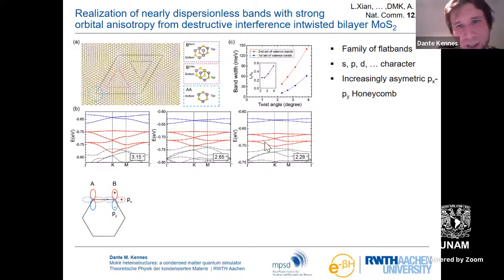And when you start to think about which kind of effective tight-binding model would give you such dispersion, you can see that you should think about a honeycomb lattice with orbital degrees of freedom px and py, where you have extremely asymmetric hoppings between px to px versus px to py. This asymmetry is shown in this inset here, again in dependence of the twist angle. As you can see, as you go to smaller twist angle, you can tune this asymmetry to a much, much smaller value. And this is interesting because when you go to the extremely asymmetric limit, you would get a lattice that is akin to the Lieb lattice, where you have geometric interference leading to entirely flat bands. Yeah? So we have now two types of flat bands. The one flat band is engineered by the Moiré effect. Yeah? So this is the overall bandwidth.